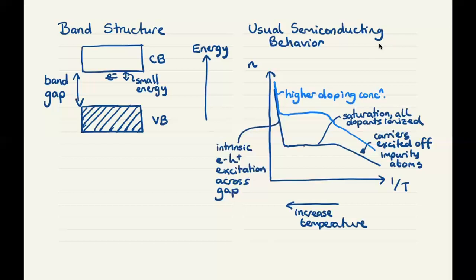Until the doping concentration becomes so high that we reach what's called the degenerate regime. And in that regime, the number of carriers as a function of temperature is approximately constant. And this is called the degenerate regime. So it's the degenerate doping concentration. And it usually corresponds to doping concentrations of greater than roughly 10 to the 18 per centimeter cubed.